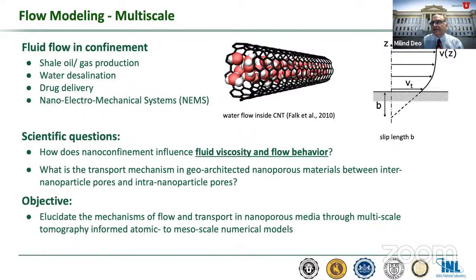Some of these experiments at the nanoscale are very difficult, particularly the pressure-driven flow, because you actually have to seal the materials at very high pressure flow. So eventually we will have to do the experimental validation or confirmation at larger scales, right? Even that capillary that I showed you was a 75 micron capillary. So to model the flow in that complete system, we need to go beyond molecular dynamics.